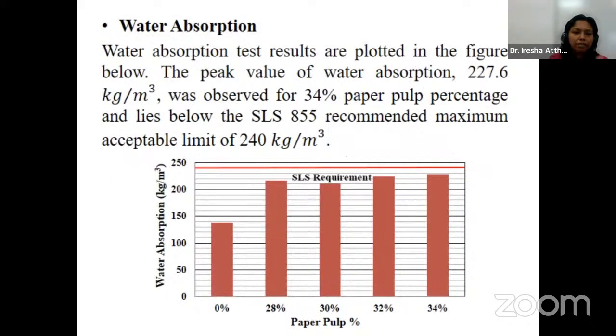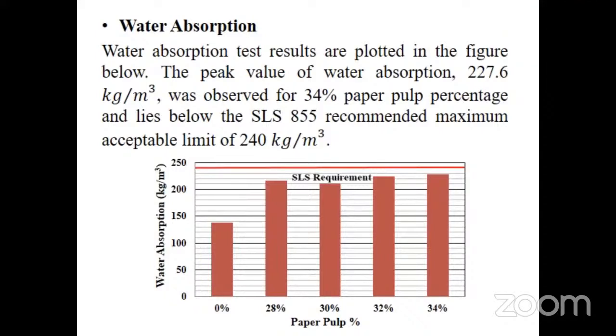Now it is time for water absorption. This test was carried out conforming to SLS 855 Part 2 of 1989 as shown in the figure. The peak value of water absorption of 227.6 kg per meter cube was observed for 34% paper pulp replacement. It also lies below the SLS 855 Part 1 recommended maximum acceptable limit of 240 kg per meter cube.